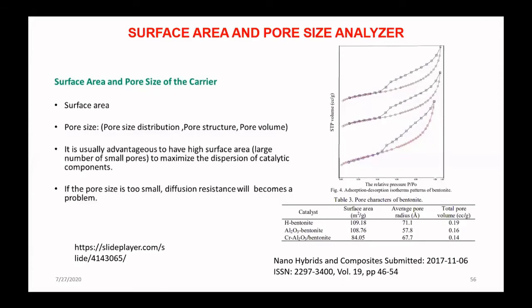This is an example of our research: the adsorption-desorption isotherm pattern of bentonite before and after being treated with alumina. Of course, we don't use alumina oxide directly. We use a precursor, aluminum chloride, followed by hydrolysis, and then oxidation, and we obtain alumina bentonite, and insertion of chrome through a salt of chromium, followed by calcination and reduction using hydrogen gas. We see from this picture that there is a hysteresis. This means there is a pore in the materials.